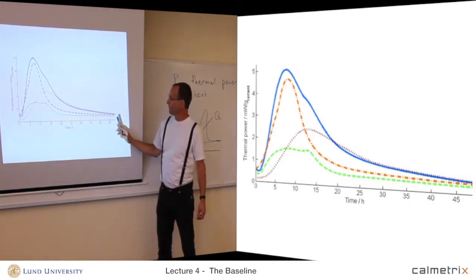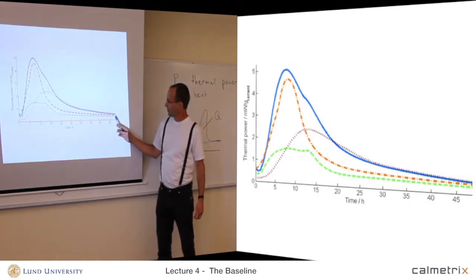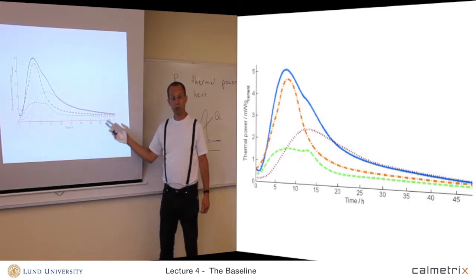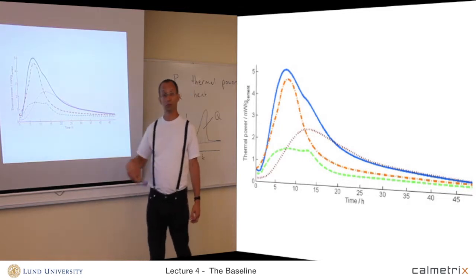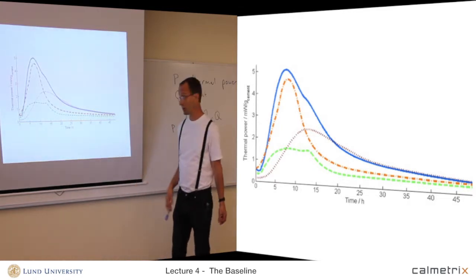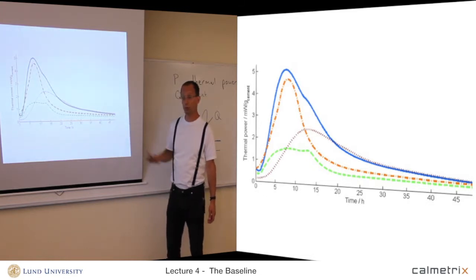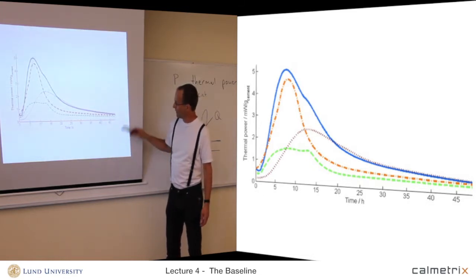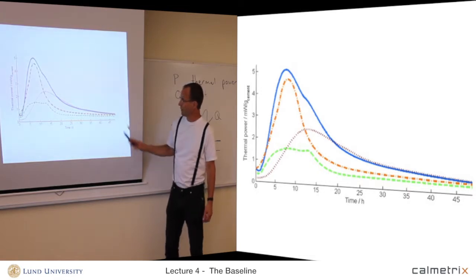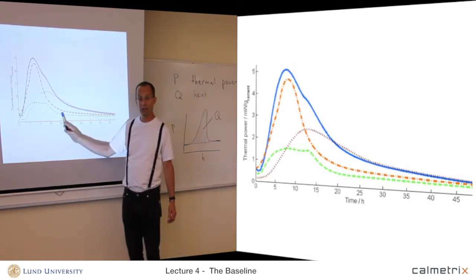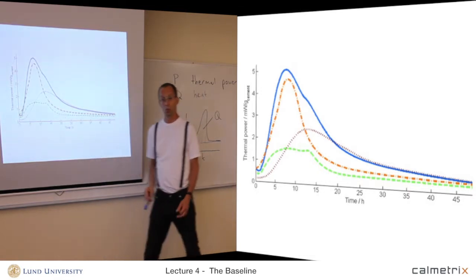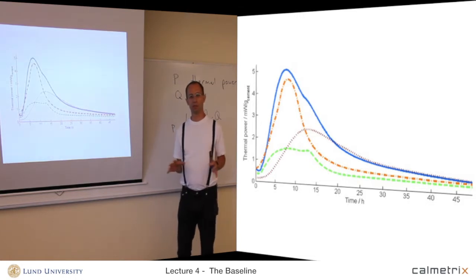And cement hydration is a very long-term reaction — concrete can actually keep getting stronger even after a year, so the reaction almost never stops. It's not finished at the end of the measurement either. So there is no baseline to be found. For cement hydration, we need to measure the baseline in a separate experiment.